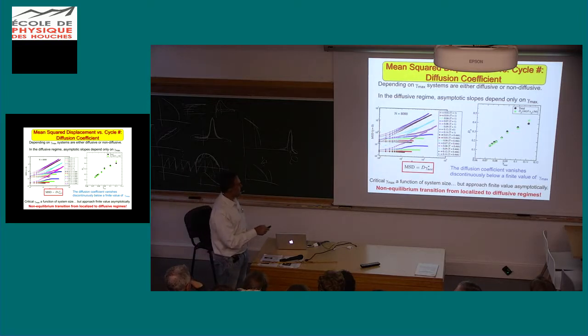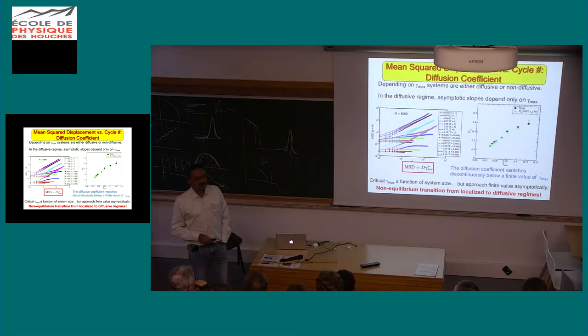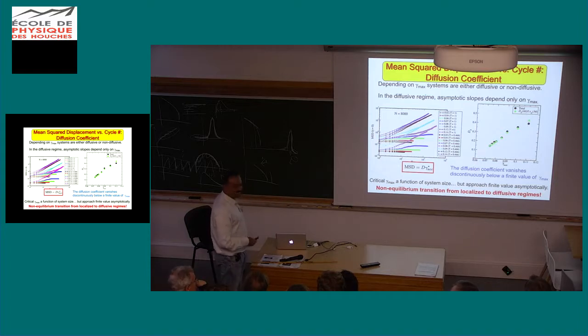Okay, so if we plot the diffusion coefficient obtained in this way as a function of the amplitude of strain, one finds that in the higher strain amplitude regime, there is a finite diffusion coefficient that abruptly goes to 0 below a certain strain amplitude. I know you're smiling for a reason. Whether this was a sudden jump or not was not very clear, but work of Kawasaki and Berthier showed that this was a sudden jump, and we've been subsequently able to confirm that to be the case.